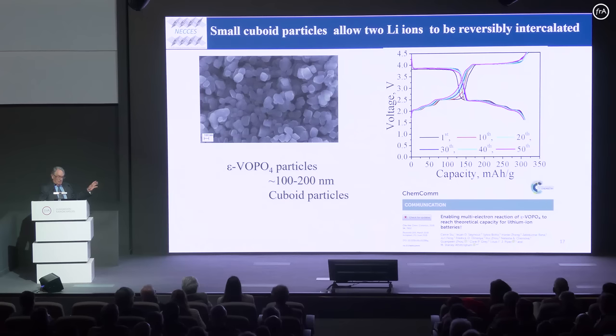And you can see we've now got two plateaus. We've got a 4-volt discharge and a 2.5-volt one. The 4-volt is the +5 to +4 and the other one is +4 to +3. And we can go backwards and forwards, and those of you who have good eyesight can see the black line is the first cycle, the purple one is the 50th. So the 50th cycle is in fact slightly better than the first cycle. So we've got proof of concept. We can have a crystal lattice that will happily take up two lithium ions reversibly without destruction of that crystal lattice. So we're pursuing that now and trying to solve some of the other issues with it. The major issue with this material is that it's a known oxidation catalyst, so it likes eating up our organic solvent molecules. So we have to solve that, but the material itself is perfectly stable.